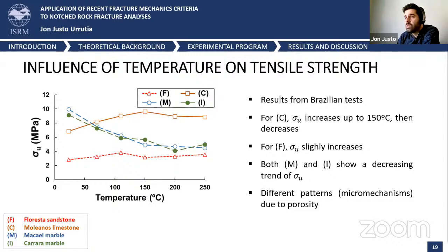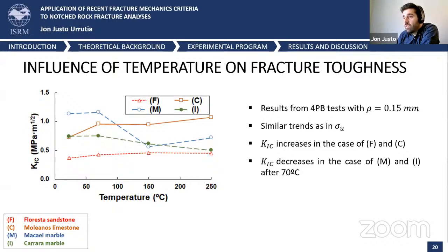These behaviors are related to two different micromechanisms. In the case of the porous rocks, the Floresta sandstone and the Moleanos limestone, the tensile strength increases for moderate temperatures due to the partial closure of pores or other pre-existing or persisting microcracks. And once a certain critical temperature is reached, thermally induced new microcracks arise, and as a consequence, there is a strength reduction. That's why in the case of the non-porous rocks, the marbles, as there is no internal space for the expansion of the crystals, the tensile strength is reduced from the onset of the heating process. This other plot represents the variation of the fracture toughness with temperature, and relatively similar trends to those observed in the tensile strength are seen.